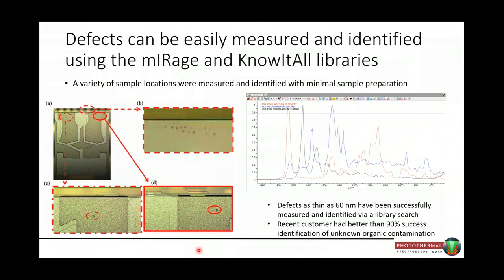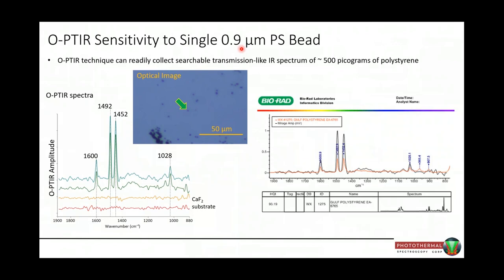It's also sensitive to a single, in this case, 0.9 micron diameter polystyrene bead on the surface. Again, we can see one of those beads, collect spectra on the bead and off the bead, and clearly get a spectrum that's library searchable and easily identified as polystyrene.